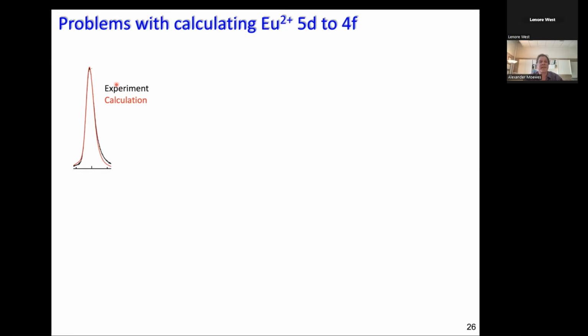Now, the next thing is the energy or the wavelength of this. So this is, of course, visible light here now. Anybody who's ever also done a DFT calculation knows that it is not possible, especially in the visible range, to predict the exact emission wavelength with great certainty. In other words, you generate in a calculation a Gaussian peak where the height is relatively random and the position is, well, somewhat random. Of course, it has some meaning, the energy, but it would not be suitable to do predictions of where the energy exactly lies.